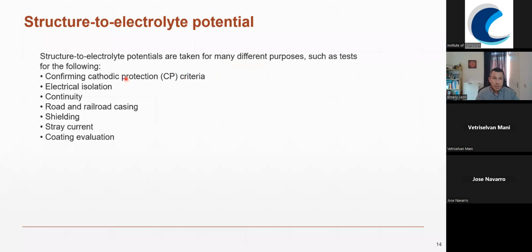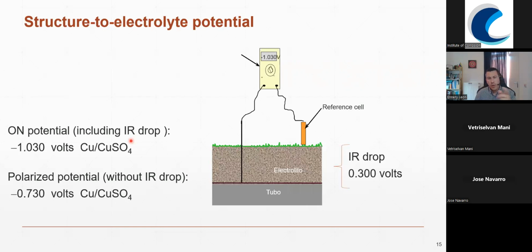So first, it helps us to confirm if our CP system is following the criterion that we choose. We can also use this one to check electrical isolation, the continuity of a structure, when we have issues with a road or a railroad casing, shielding effect, stray current, or a coating evaluation. It's important to bear in mind that when we are executing this survey, we need to make sure that we report the IR drop free potential.